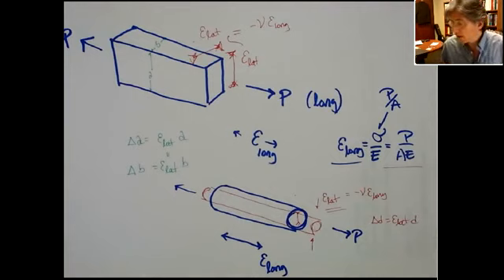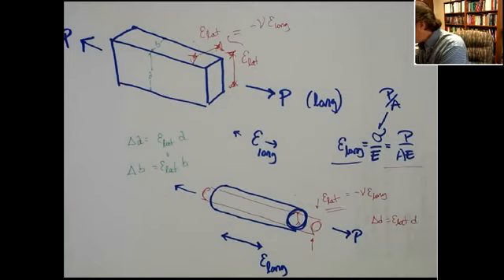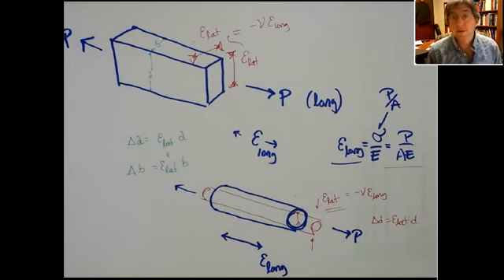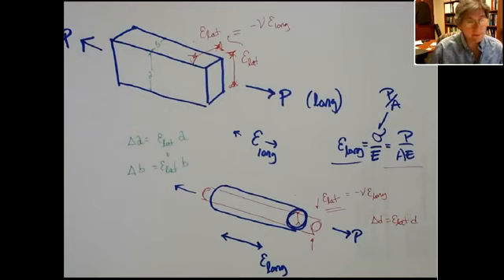A lot of times we kind of look at it as a 2D effect, but really it's a 3D effect. It's elastic. There also is a Poisson effect in plasticity, and you can see that especially with necking. In the tensile test video, you can see the necking when there's plastic deformation — and that's the Poisson effect in plasticity.